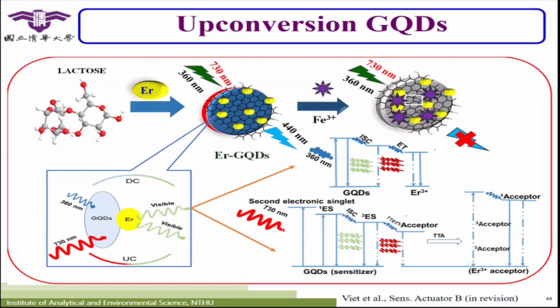Just think about solar energy. For solar energy, people would like to use visible light, even the IR region, so they can enhance light penetration and light harvesting efficiency. But it seems quite hard for us at this moment to use the long visible light and near IR range. So if you add the upconversion GQD inside, they can use the long visible light, 730 or even 900 nanometers. They can recover the low light, and your solar energy becomes more efficient. So that is the case.